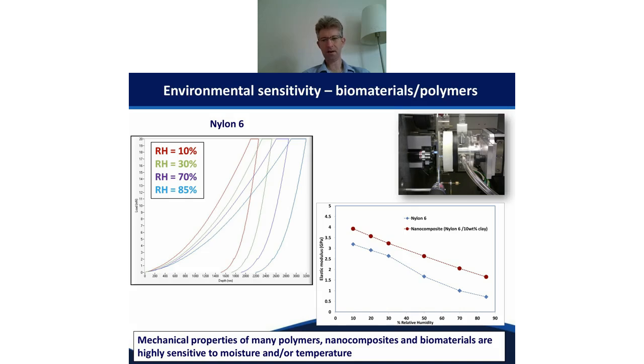You can see how the users then moved to developing a new improved material by putting a clay into that material, intercalating a clay, and that increases the stiffness of the material. But you can see that relative stiffness enhancement is not constant across that humidity range. The enhancement in stiffness is much, much better in the composite material at high humidity. So this is very useful for applications where the nylon might be susceptible to very moist environments and is suffering from not enough structural integrity. It shows that there's a real benefit in making the composite with the 10% weight of clay in there.